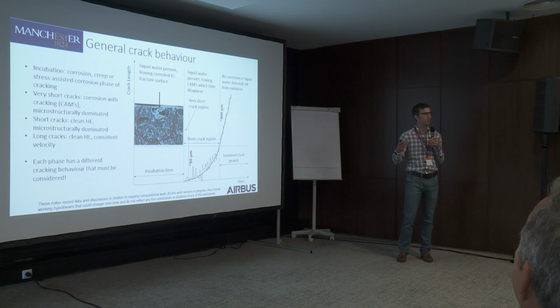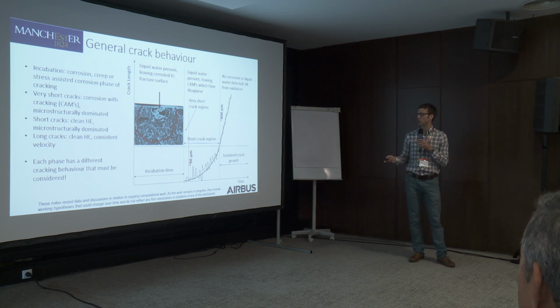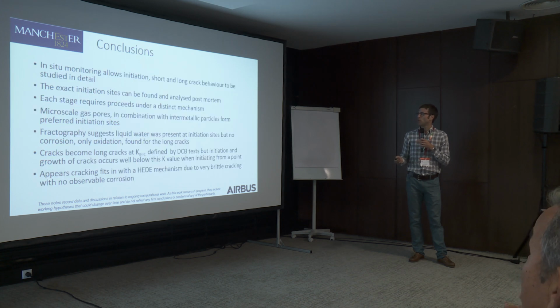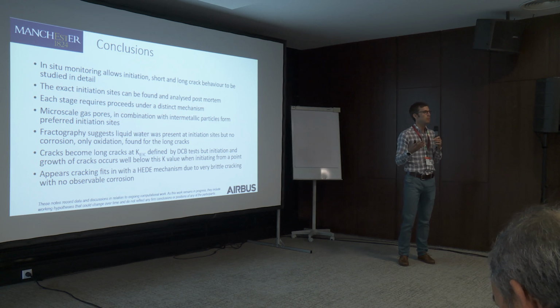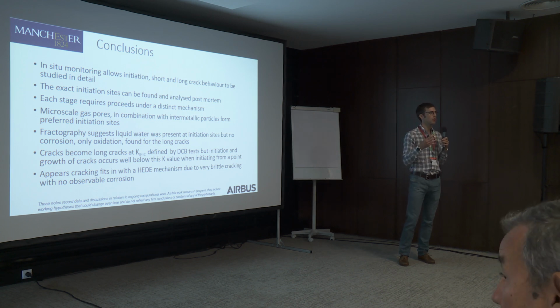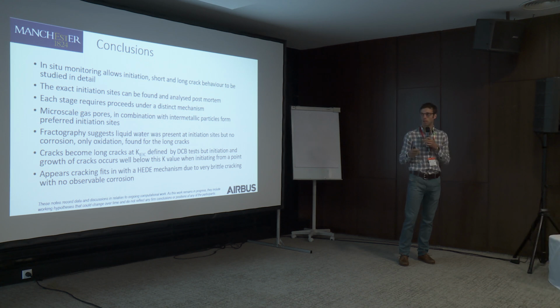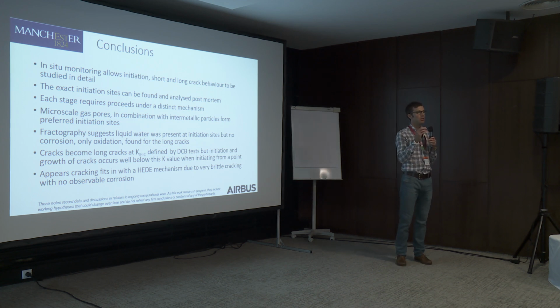And then we eventually reach a sustained propagation phase where we get a much more consistent growth of the cracks. So, in summary, we've built a system which has allowed us to observe the initiation and short crack and long crack growth of these cracks in the humid environment for the high strength aluminium alloys, and that's allowed us to go in and find that exact initiation site and then analyze that and say what the conditions are. And the point I'd like to make is that at each one of those stages that I've introduced, we've really got quite a distinct mechanical and environmental scenario. So we really have to consider that when we're building our models and thinking about what mechanisms are important for those different stages, because mechanistically they are distinct.